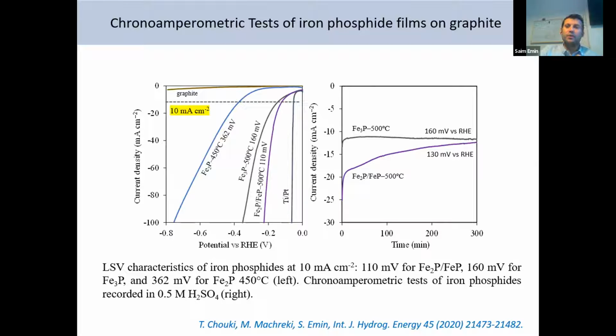After synthesis, we need to heat the films because we need to remove the organics on the surface of the particles. They block the catalytic activity. So the heating was done at 500 degrees Celsius under a reductive atmosphere. We use this reductive atmosphere for a purpose: we can also cause some kind of phase transition inside the material by heating in a hydrogen atmosphere.